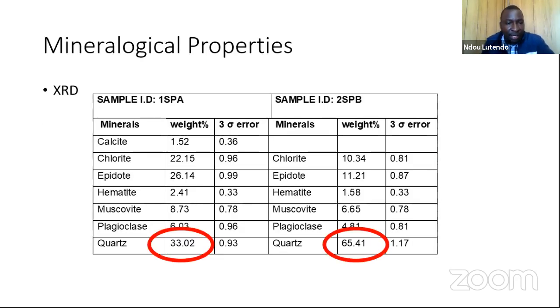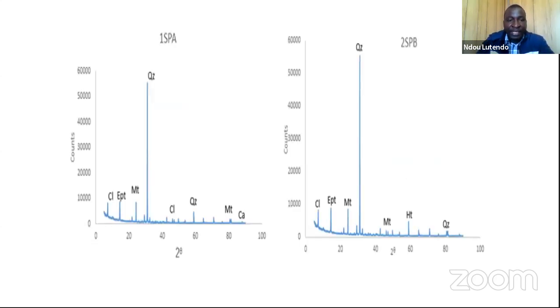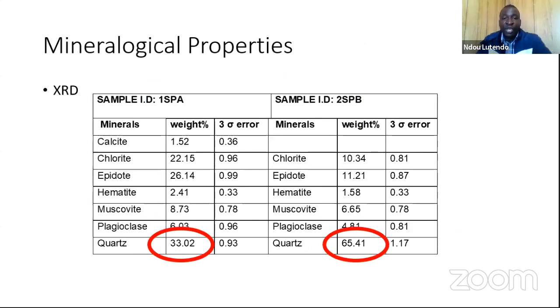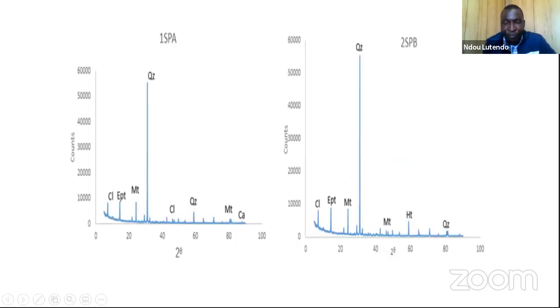Mineralogically, you can see these materials had over 33% of quartz on sample 1 and over 65% of quartz on sample 2. And you can see some of the minerals such as epidote that has aluminum in them. They had high concentration, which is 26% and 11% on the other sample. So basically, this is just a graph showing you the composition of the minerals that were there in my sample for both sample A and sample B.